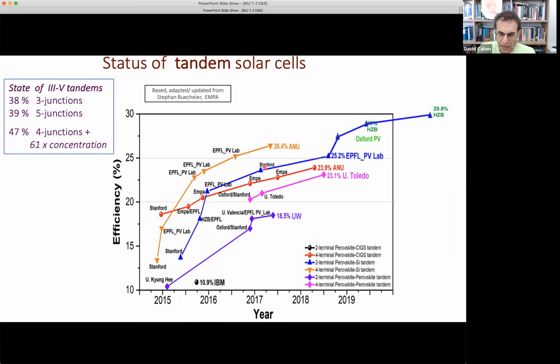And the halide perovskites have been investigated intensively for the tandem cells, even if the articles that draw the attention are for the single junction cells, which would compete with silicon, which is not really going to work in the near future, in my opinion. So instead, a big effort has been on making tandems of silicon and halide perovskite, or copper indium gallium selenide, which has a small band gap, and halide perovskite. Silicon has a small band gap. And the best result is here from the Helmholtz in Berlin, nearly 30%. That has been achieved early this year.